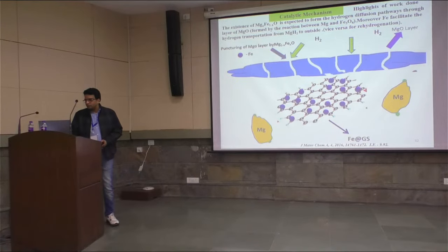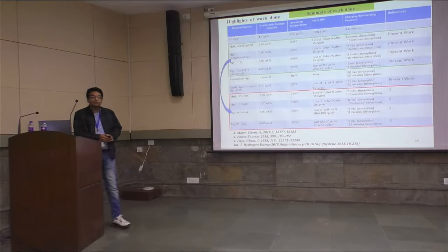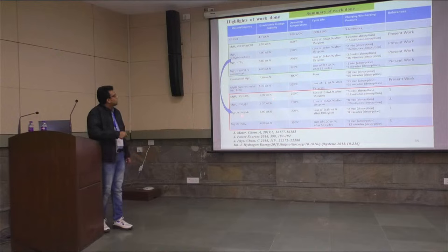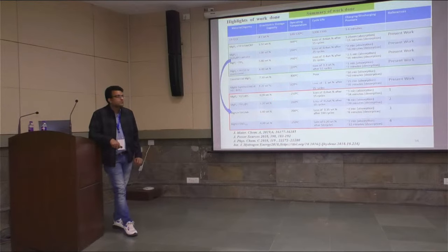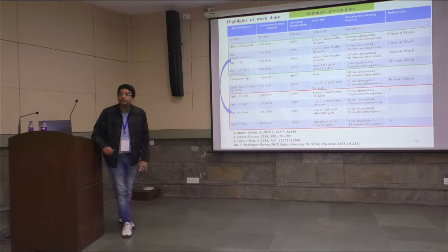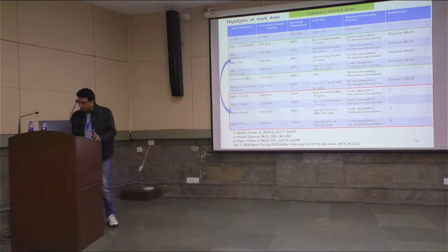I am skipping this part in order to quickly summarize the talk. So these are a number of catalysts. I have shown you one catalyst that can lower the desorption temperature of magnesium hydride. And these are the catalysts that we have used, and you see that we have obtained a desorption temperature of 220 degrees Celsius, and the materials work for around 500 seconds. I am skipping all the details.